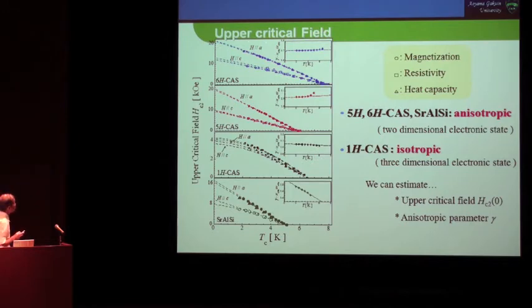If we apply H parallel A and H parallel C, the upper critical field shows strong anisotropy. However, surprisingly, 1H CAS reaches almost the same value, so-called isotropic. Also, strontium aluminum silicon has strong anisotropy. I don't know why such big differences exist.